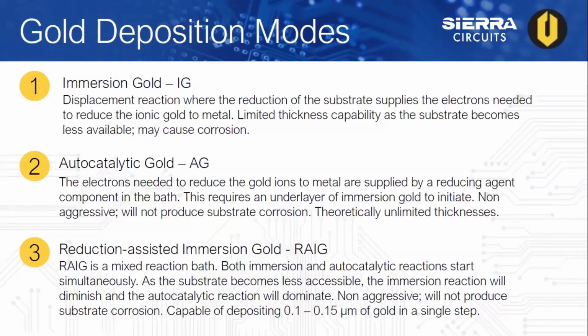Two is the autocatalytic gold. The electrons needed to reduce the gold ions to metal are supplied by a reducing agent component in the bath. This requires an underlayer of immersion gold to initiate. It is non-aggressive and will not produce substrate corrosion. Theoretically, it can have unlimited thickness and keep plating.